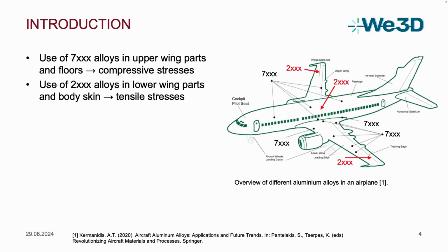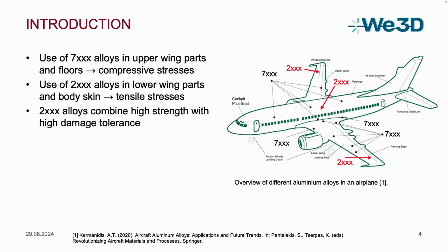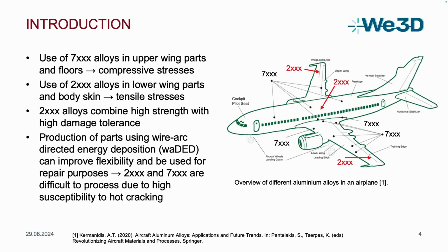So for the introduction, basically, there are two families of aluminum alloys in airplanes: 7,000 alloys for upper wing parts where we have compressive stresses, and 2,000 alloys in lower wing parts where we have tensile stresses. And basically, the 2,000 alloys combine high strength with high damage tolerance. And the idea is that we apply wire arc additive manufacturing to use the higher flexibility of the process and also for repair purposes. But there is one problem for these alloys. They are both highly susceptible to solidification cracking.